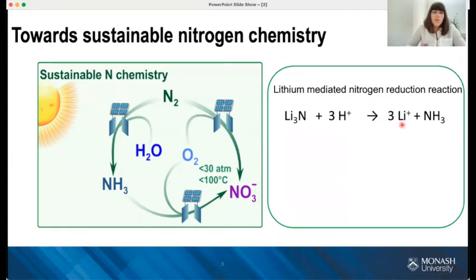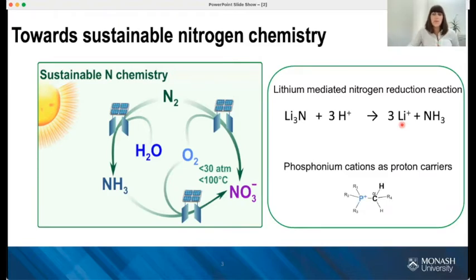Currently, research is focusing on ethanol as the sacrificial proton donor. It's sacrificial, which means it is not fully regenerated, and that really limits the performance and longevity of this process. So our goal was to develop a proton carrier that will be electrochemically stable and won't be consumed during the process. And for this purpose, we investigated phosphonium-based cations, as you can see here on the figure.